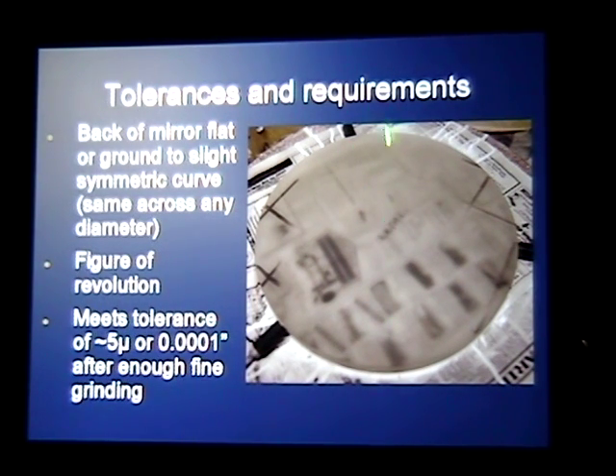This area was high. It wasn't flat, right? And it's not flat yet. So I need to continue grinding the back of this mirror down to whatever abrasive I choose, typically 5 to 12 micron, in order to make the back of this mirror flat. Otherwise, when you press on this mirror with any pressure when you're polishing, this part will bend down more than this part will, and you'll end up with an astigmatic blank.